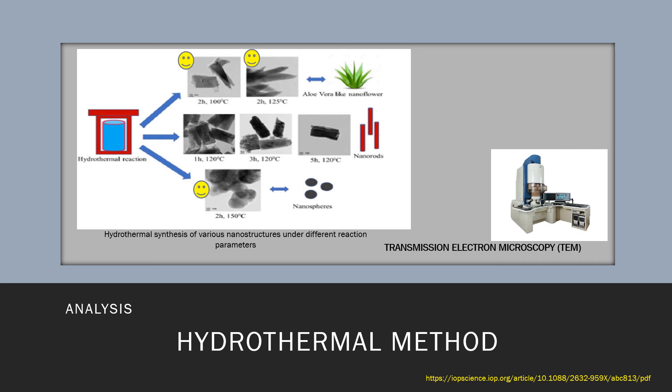Based on the results, the experimental procedure is repeated for 100 degrees Celsius temperature for two hours, and 125 degrees Celsius and 150 degrees Celsius of temperature, keeping it at two hours. So the duration of time is constant with different temperatures. As you observe, the three yellow smiley, the other samples synthesized at a constant temperature of 120 degrees Celsius for reaction times of one hour, three hours, and five hours. So different time durations with constant temperature.